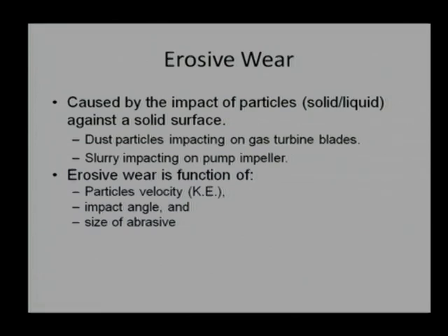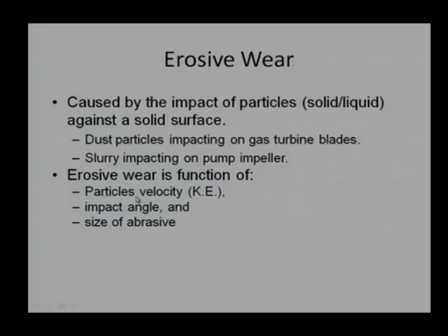So, the overall mechanism is related to kinetic energy, and particle velocity is related to kinetic energy, but we say strong dependence because it comes as v squared. While for the mass, if we assume a spherical particle, then the third power comes with d cubed. Particle size will be proportional to d, and then volume will be proportional to d cubed. So again there is a severity, there is a strong dependence on the particle size. So, particle size as well as velocity are going to strongly affect the amount of wear, while the impact angle depends on which material we are using, and that will affect the impact wear or erosive wear.